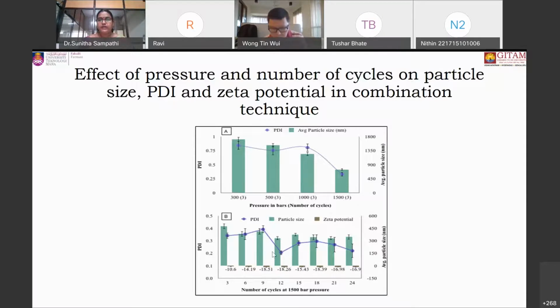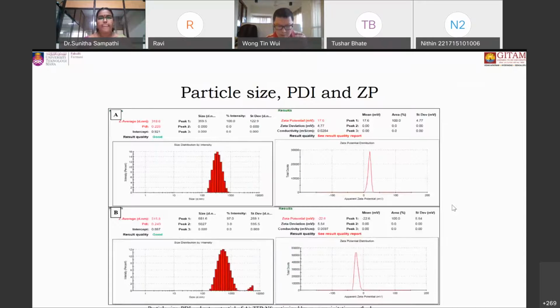So that means at 1500 bar, for 12 cycles, the nanosuspension is giving a low particle size of around 350 nanometers. This was measured with the Malvern Zetasizer. And a further increase in the number of cycles did not have any effect on the particle size. So we thought of continuing with the high pressure homogenizer at 1500 bar for 12 cycles. Now, this is the particle size, PDI and zeta potential, which was measured with the Malvern Zetasizer. Here you can see that the particles have very good uniformity with a low PDI and a good zeta potential.